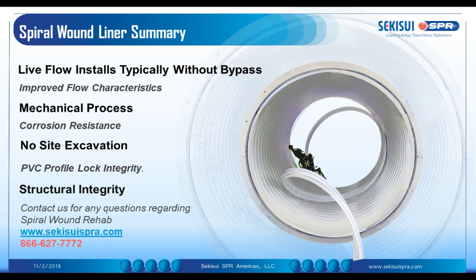What is the Manning's equation for the liner once installed in a pipe? The Manning's equation or the Manning's factor? Manning's factor, sorry. Yeah. We employ a Manning's factor of 0.009. I mentioned during the presentation that we have conducted testing of liners at small diameter in both laminar and turbulent flow conditions. Our testing achieved values ranging from 0.008 to 0.0094, and we employ 0.009 to be consistent with industry expectations for plastic pipes.